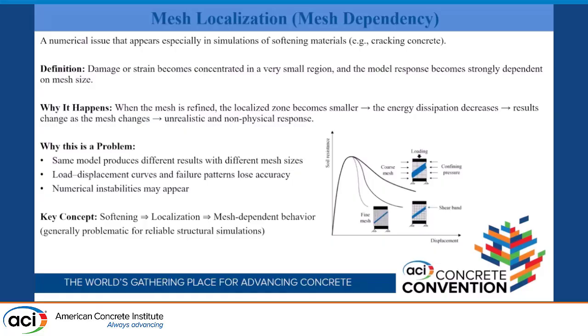But if your numerical model gives you artificial softening, in that when you refine your mesh, you nominally expect your finite element method to give you a better result. But if your result is constantly changing, like you're seeing in the picture here, as you refine your mesh, your post-peak response is changing, then it's going to be a problem. Even if your objective is to capture the peak loads in a given structure, this is still a problem because your structure will not fail uniformly. Failure will be, again, localized somewhere. And if that failure is not correctly represented, other parts will get different loads than they would have. So even then, the overall load might be misrepresented.